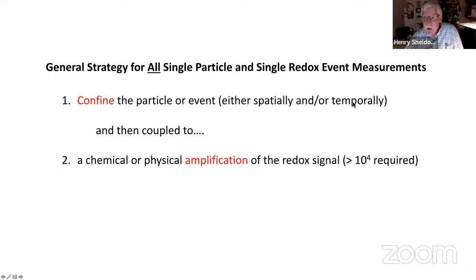So get down to a few particles or a few molecules by constraining the space you're working in, or by doing fast measurements. And then you have to couple that to some type of amplification. It could be a chemical or physical amplification, but because you can't see single electrons, there has to be an amplification. And it turns out the amplification that's usually required is always about 10 to the 4th, 10,000 or greater to do these measurements. Okay, so let's take that rule that you have to have confinement and amplification.